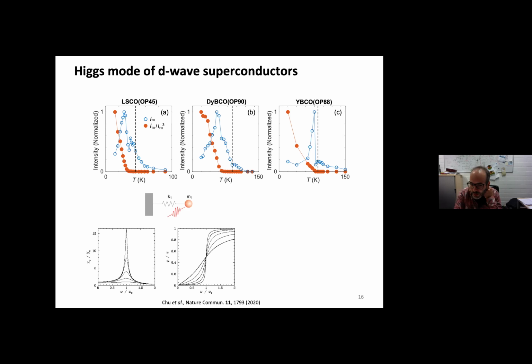If you want to figure out how strongly a system is damped, then we can think of a normal harmonic oscillator. And we know, of course, in a heavily damped system, the resonance of the amplitude becomes smeared out strongly if we start damping. But a very good tool to measure the strength of the damping is to look at the phase response of such an oscillator. Because in an underdamped oscillator, the phase response makes a pi phase jump from low to high at the resonance frequency. And if you have a heavily damped system, this pi phase jump smears out.